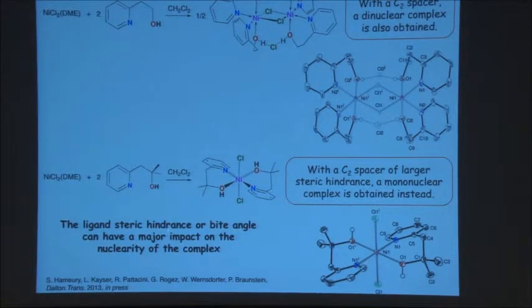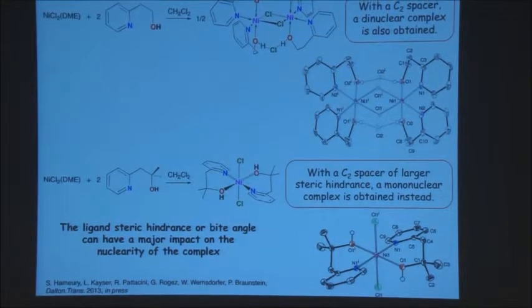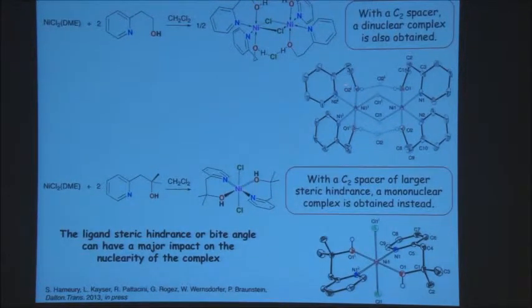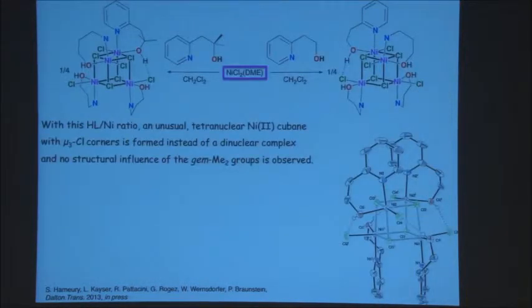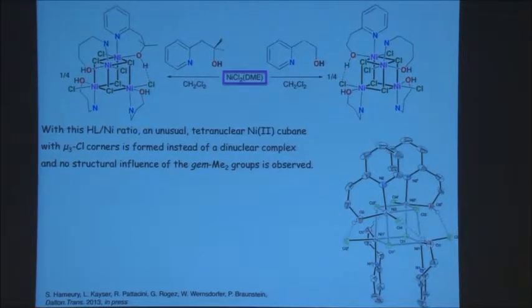So you see here, between these two systems, you can directly identify the steric consequences of the two methyl groups here. They prevent formation of a dinuclear species because there would be a steric clash between the methyl groups of each side. They would clash sterically. That's why the dinuclear structure is not favored, rather the mononuclear system is. So we have here a case where there is indeed an impact on the structure. Now the question is, how does that translate in catalysis?